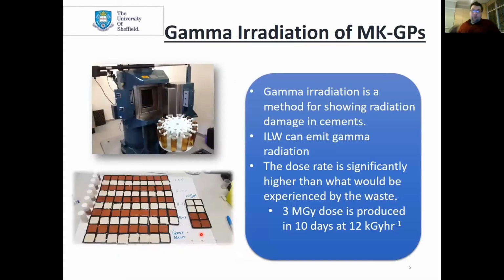Here is the irradiator I used at the University of Manchester's Dalton facility. They very kindly allowed me to put my samples in there for 10 days. When I ran these samples, we decided I could have got a higher dose, but it would have been an incredibly high dose rate. There are always arguments in the literature about dose rate versus total dose effects, so we picked a middle-of-the-road dose rate to get a relatively high dose.